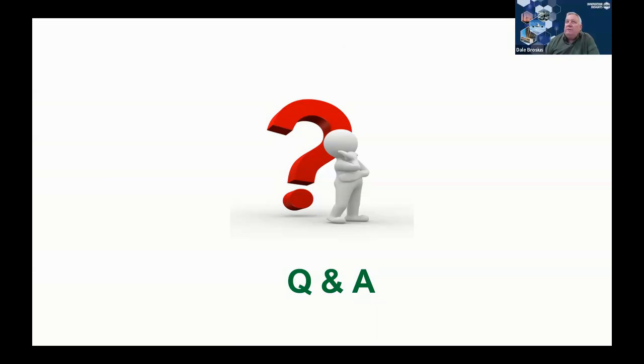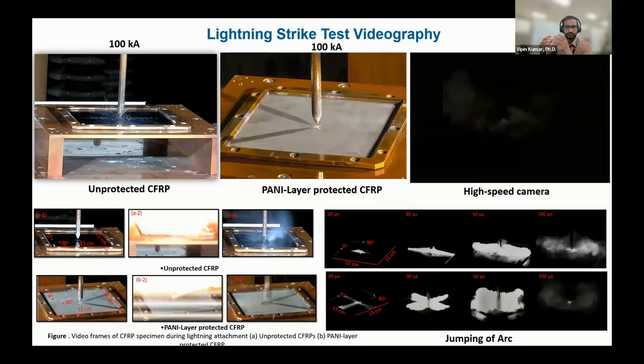And how would you compare this method to the mesh? Because I noticed you didn't do an uncoated epoxy and then a coated epoxy, so how would you compare it to the mesh technique that's commonly used? So mesh is by far good, it's the state of the art. What I'm providing is off the shelf. If you have something you want to just go and paint, you don't have to put the mesh inside. With the mesh, you have to put the mesh and the carbon together and co-cure them together. But in this case, this is like a paint. You just go and brush it and get it cured. So this is an off-the-shelf product, let's say.